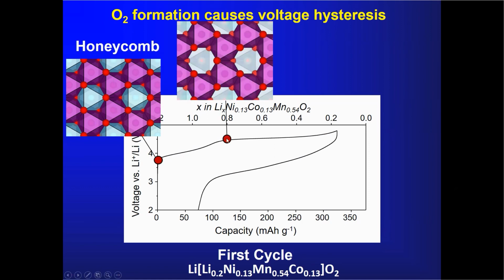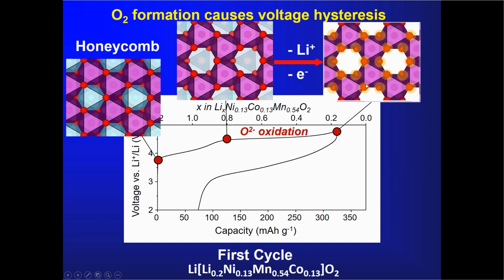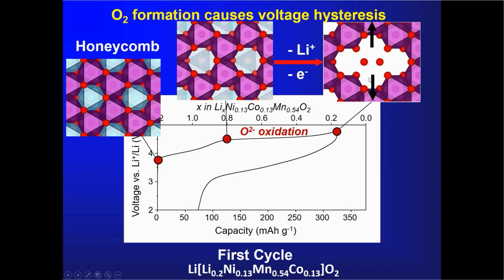Now we have, at the end of the normal transition metal redox region, removed lithium ions and oxidized transition metal ions. Then we will progress across the plateau. Now we have removed more lithium, all or almost all the lithium is gone, and we've oxidized oxide ions, shown by these flashing images on the oxide. Of course, when we oxidize oxide ions, we're removing charge from the bonding states, and we're weakening the metal-oxygen bond.